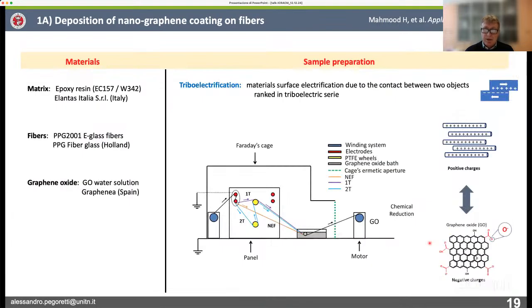In order to scale up the process, because for electrophoretic deposition the equipment we used was a very small one, we use another technique, which is triboelectrification. It is a very simple concept. When you slide two different materials on top of each other, you can generate charging in both of them, and by selecting the proper triboelectric series, you can force positive charges on the surface of glass fibers.